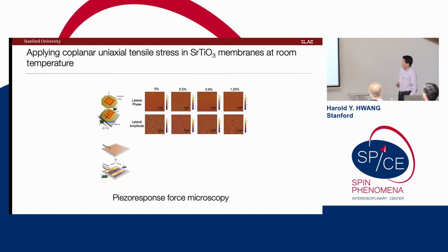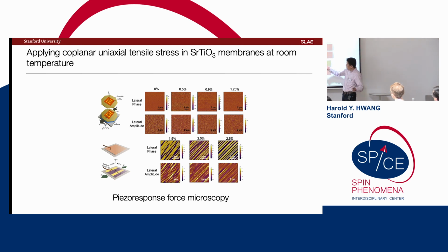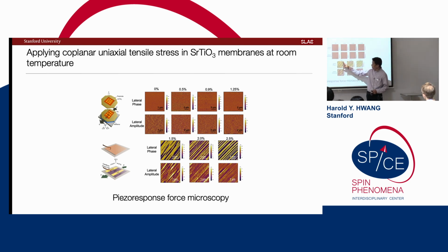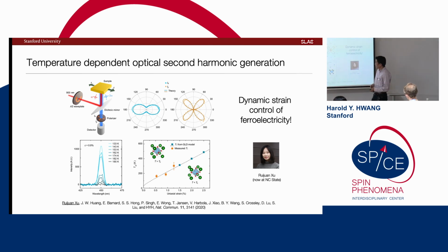Another example, in this case of uniaxial strain: a lot of this community has been playing with the soft mode dynamics of strontium titanate. Here we stretch in one direction, using piezo force microscopy. Basically, we see nothing, nothing, nothing at room temperature, and suddenly above a critical strain, you can see the induction of ferroelectric domains in the response. Again, a lovely system. Obviously we knew where to look because people had previously shown you're very close to this ferroelectric instability.